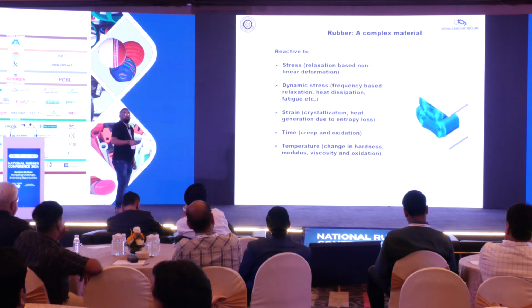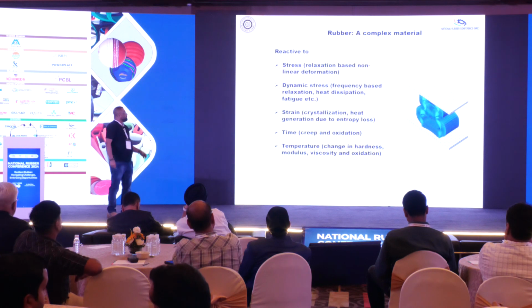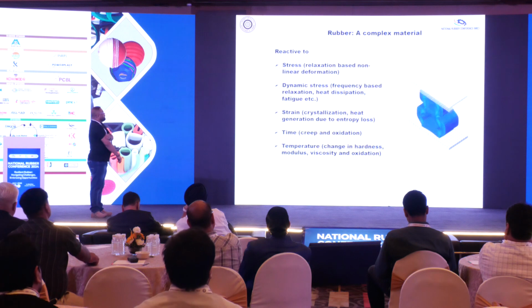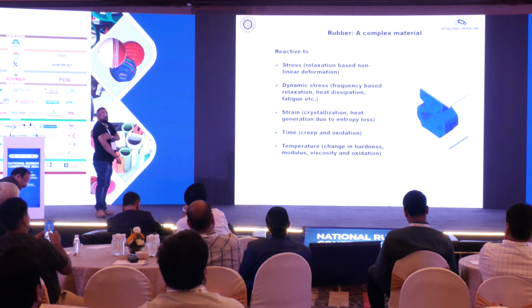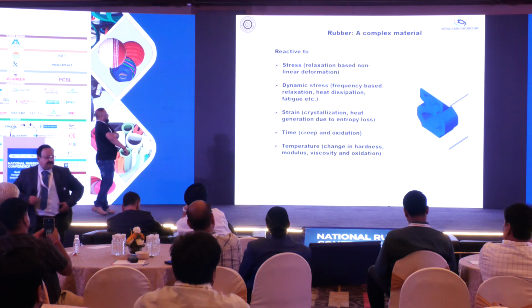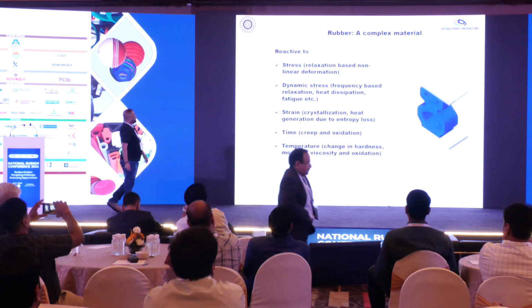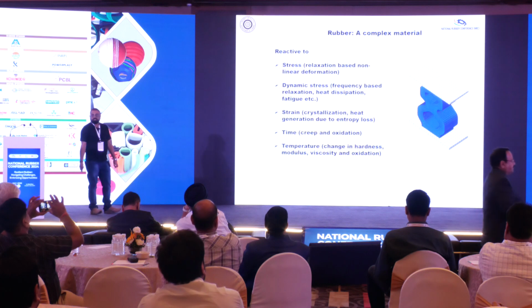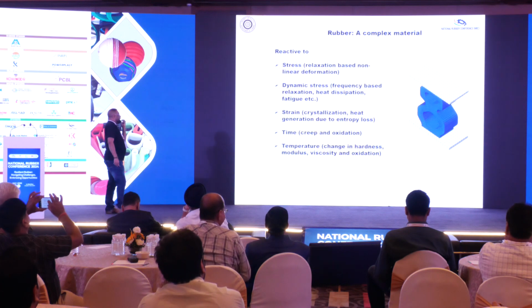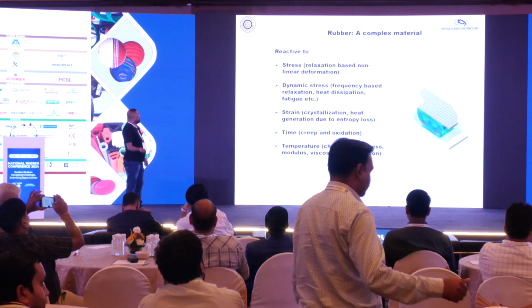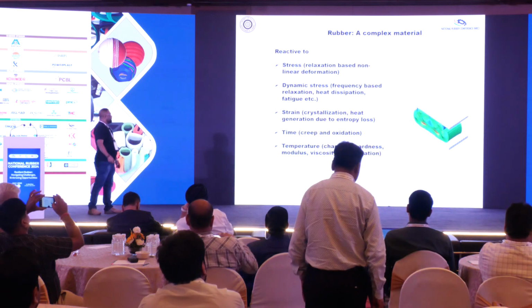Now, why is it important for rubber products? Because we know that rubbers are highly reactive to stress, as they give a relaxation-based nonlinear deformation. Under dynamic stress, they give frequency-based relaxation, heat dissipation, fatigue, etc. Under strain, they give crystallization and heat generation due to entropy loss.